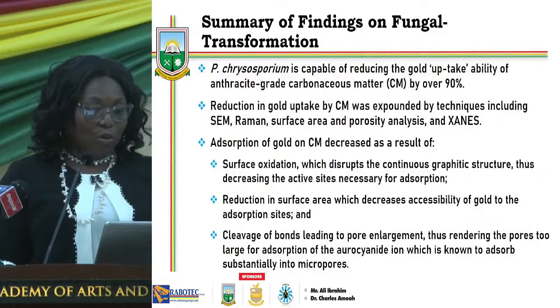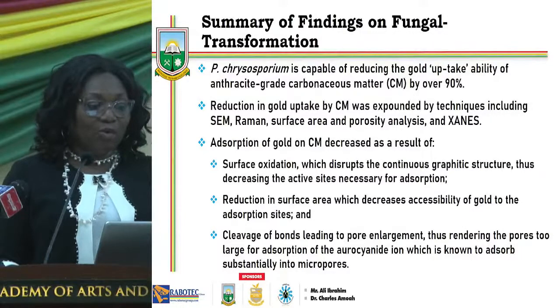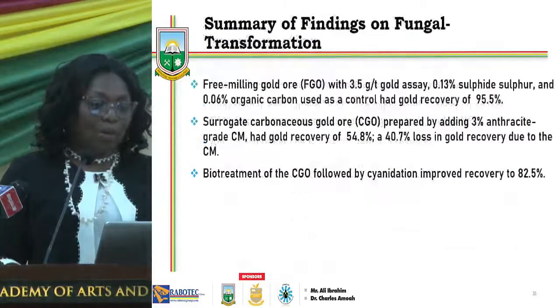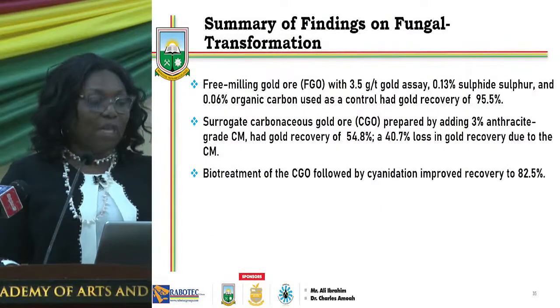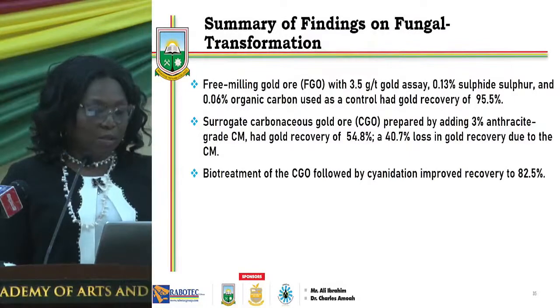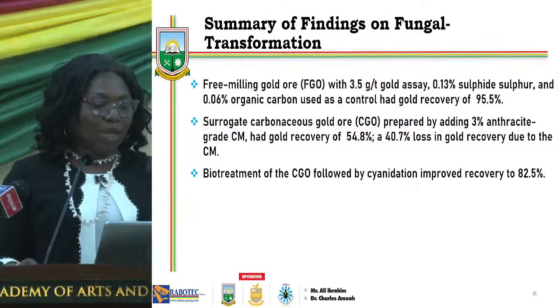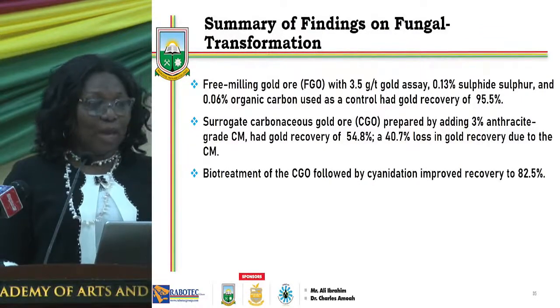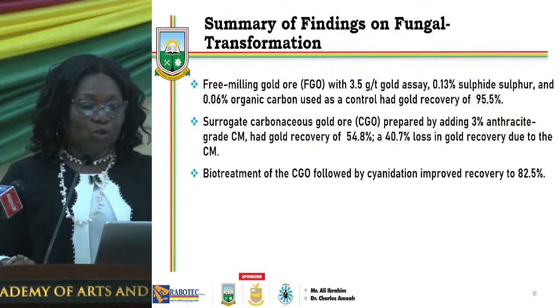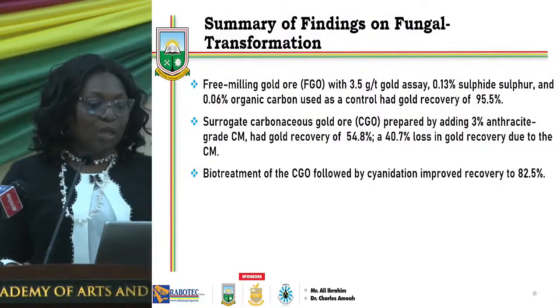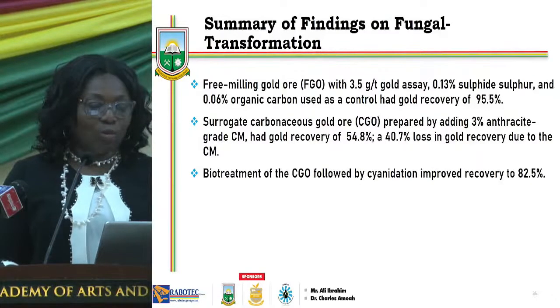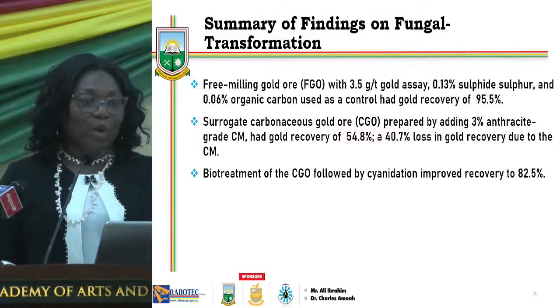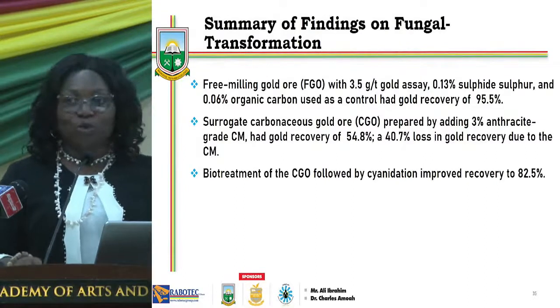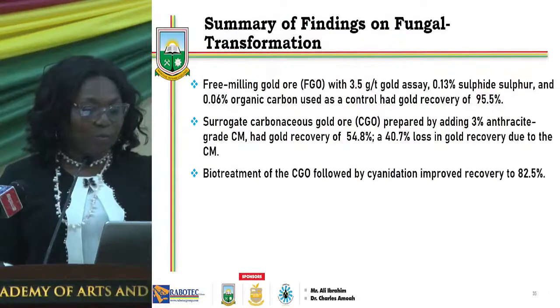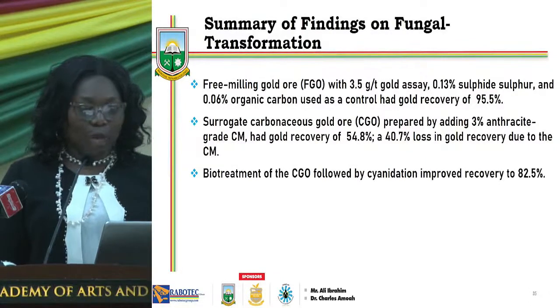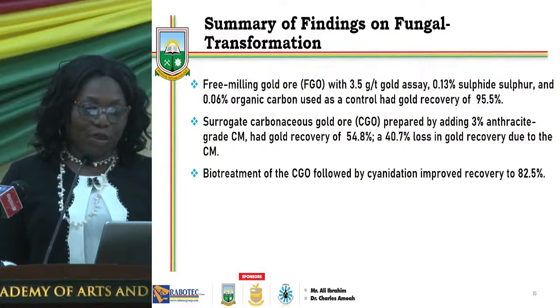Free milling gold ore with gold grade of 3.5 gram per ton was able to give a recovery of 95.5%. When surrogate carbonaceous gold ore was created by adding 3% anthracite to the free milling gold ore, the gold recovery was 54.8%. And when the surrogate carbonaceous ore was treated with Phanerochaete chrysosporium, the recovery came up to 82.5%.